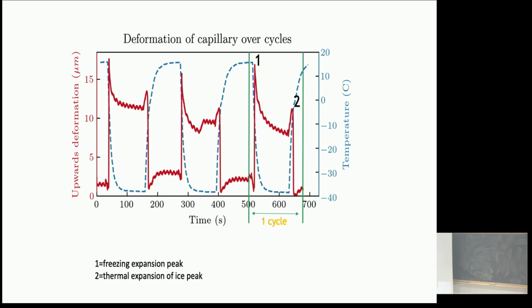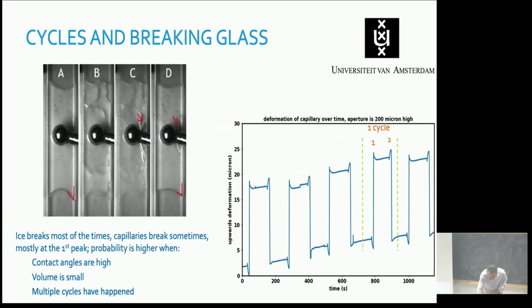But what is more interesting is that, so this is the capillary reading. When the water freezes, we get a very high peak. And this is clearly the expansion of the water when it freezes into ice. But then when we start to heat up, we get a second peak, and this is simply the thermal expansion of the ice. So we cycle, and we look at what damage we get.